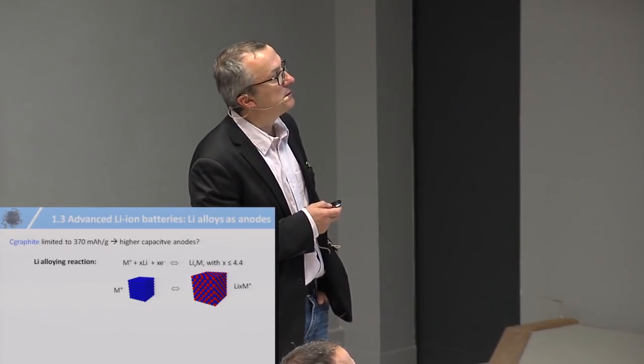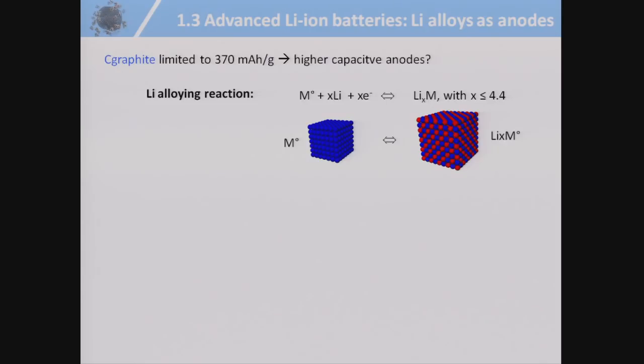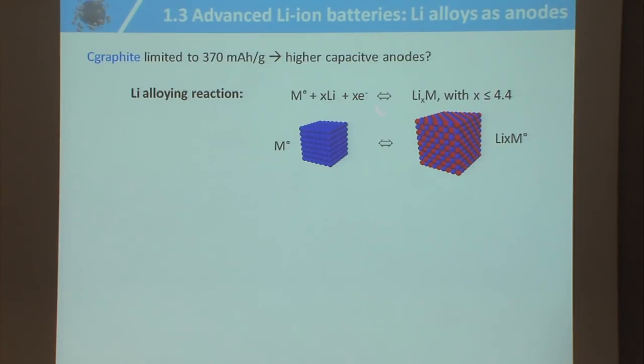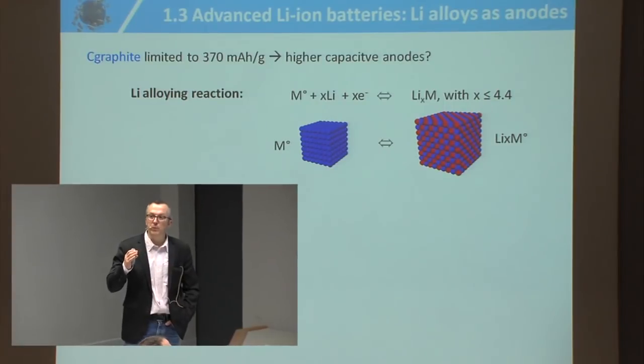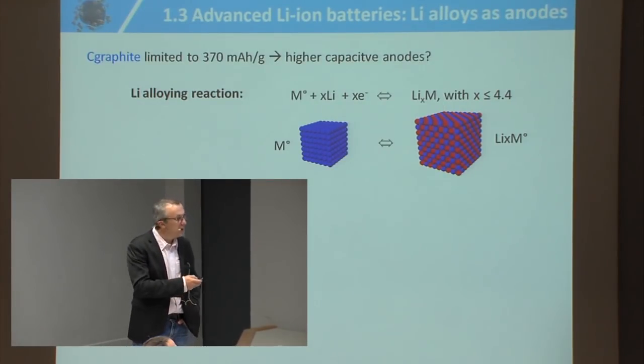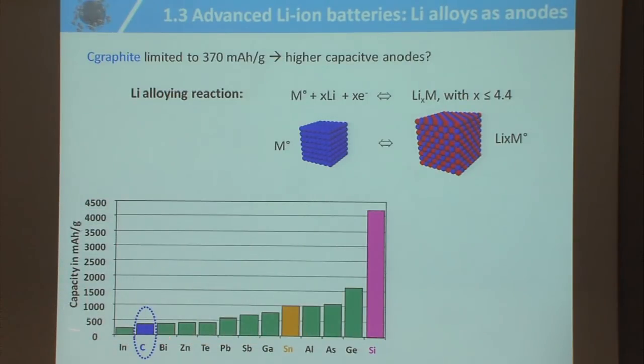And you take, for instance, a metal, and the plus is missing here, sorry, I apologize for that. And when you polarize this metal, you can reduce Li+ into the metal to form the lithium alloy. And you can put up to 4.4 lithium per metal. So now, if you have a look at the specific capacity of a metal, if you take carbon, 1 lithium, 1 Faraday for 6 carbons, means 372 milliampere-hour per gram. And you can see here, silicon theoretically can reach 4,000 milliampere-hour per gram, 12 times more. Why? Just because you can do silicon plus 4.4 Li+ plus 4.4 electrons gives Li4.4Si. And this is an outstanding high-capacity anode.